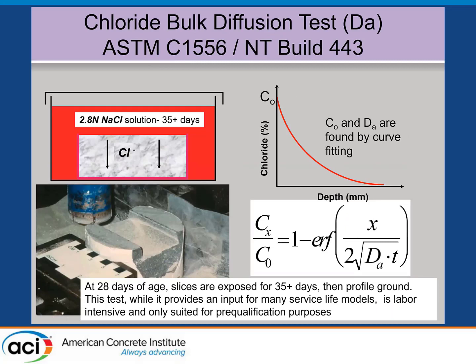Now, a lot of service life models assume that chlorides move in by diffusion. They slowly diffuse due to the concentration gradient, and they move in towards the steel. And there is a standard test, ASTM C1556, which was built on the Nord test method that existed before that. You cast concrete, you cure it for 28 days or whatever, and you seal it on all sides except one. You let the salt penetrate in of a certain concentration for at least 35 days. You profile grind it. You plot the data, fit it to a curve using a best fit equation, and you can calculate this diffusion coefficient from that using Fick's second law. And that's used as an input in many service life models.